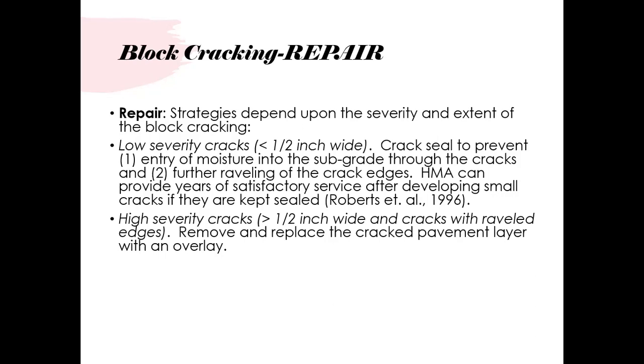If your crack is of high severity, that is half an inch wide or more, you have to remove the cracked pavement and apply an overlay. Here you cannot just apply grouting to the cracks. This will not help. You have to remove the pavement and apply an overlay.